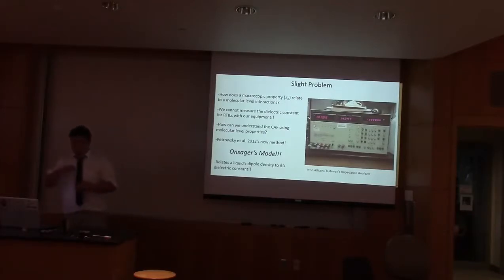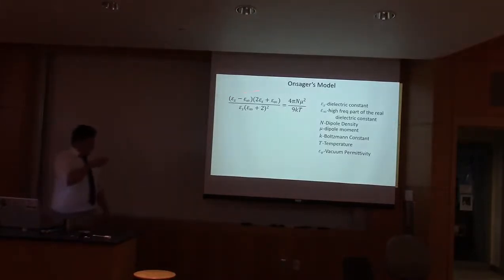This allows us now to go back and be able to relate a molecular level property as causing these differences and variations in molecular level transport properties in liquids. So I'm going to now talk about what exactly Onsager's model is and how they did that. This by itself is Onsager's model. The epsilon sub s being the dielectric constant, the epsilon sub infinity being the high frequency part of the real dielectric constant, being equal to 4 pi times the dipole density times the dipole moment squared divided by 9 Boltzmann constants times temperature.